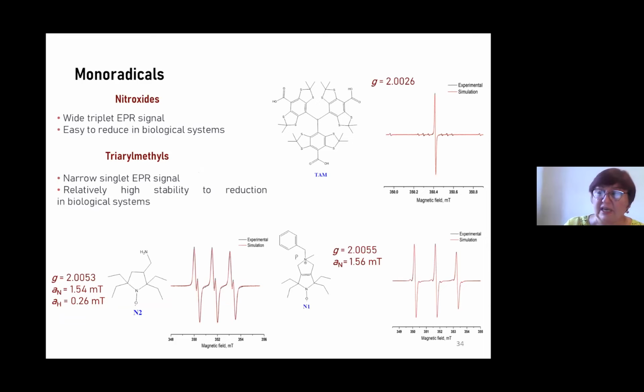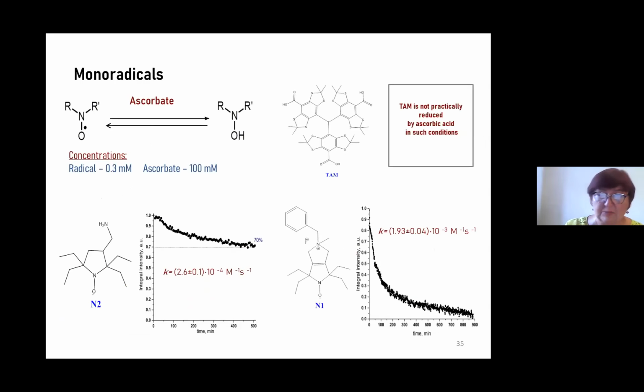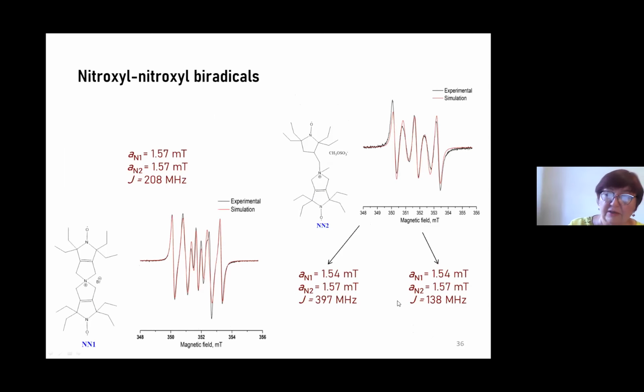And the idea was to synthesize biradicals, which are extremely stable with trityl, with this tetra-ethyl group, and to use not only TAM, but OX063, which is water soluble and very stable and has a very long electron relaxation time, but I am not sure that it's good for DNP. So all these radicals, this radical and that one, because here it has quite a good group for coupling, but unfortunately this radical is not suitable for us. It has too high a reduction rate. So such biradicals on nitroxide were synthesized, and